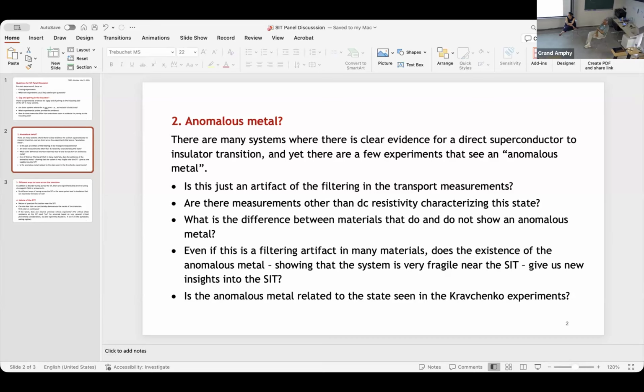Yes, but what I wanted to say is that for most of the 2D crystals, which are not from the originally disordered community, for those crystals the sheet resistance is below 100 ohms. And then you should not be surprised that this is not localized. But still, then we have to explain how it can exist. So the explanation of anomalous metal that kind of floating around.